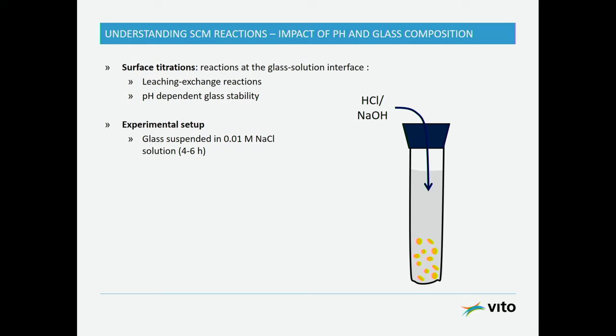Apart from just looking at the glass composition, one can also look at the pH of the solution as one of the factors that actually determines the rate of dissolution. So therefore, we did some very simple experiments in which we took the glasses we made before, and we put them in this kind of a test tube, and we added a fixed amount of HCl or NaOH, and this is called a pH titration experiment.